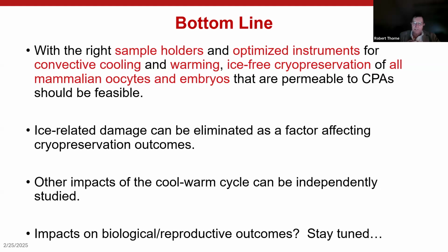And there are actually studies back in the early 2000s looking at ice formation in protein crystals, and basically nothing much happened until they got to about 180 K or so. So these are consistent with that. It's just that as you warm, the mobility of the solvent increases until eventually the growth rates really start to pick up, and you start forming big enough ice crystals to form diffraction.